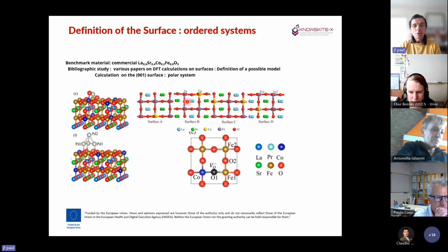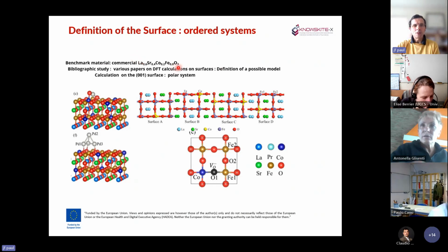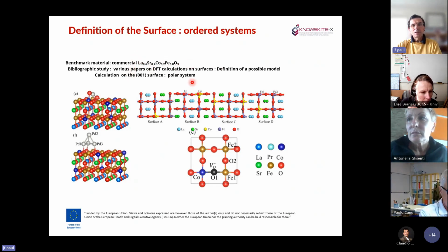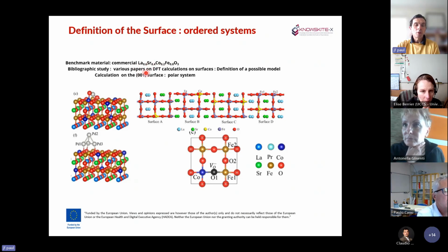Another point for the project is we need to build a model, and we will start with the lanthanum, strontium, cobalt, iron perovskite. This is an example of a material that is used experimentally. It's difficult to get exactly this type of system theoretically because you will need a lot of atoms in your cell, and the calculation will be quite large. In the literature, for the moment, one model has been proposed. You start from a classical perovskite, and you exchange one lanthanum by one strontium and one iron by one cobalt. And so it will be lanthanum 0.75, strontium 0.25, and so on.